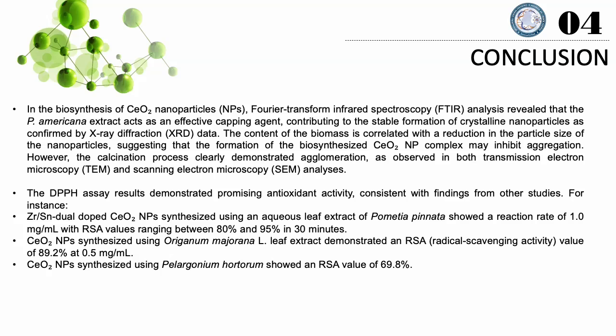Cerium oxide nanoparticles synthesized using Origanum majorana leaf extract demonstrated a radical scavenging activity value of 89.2% at 0.5 milligrams per milliliter. In another study, cerium oxide nanoparticles synthesized using Pelargonium hortorum showed a radical scavenging activity value of 69.8%, in this study.